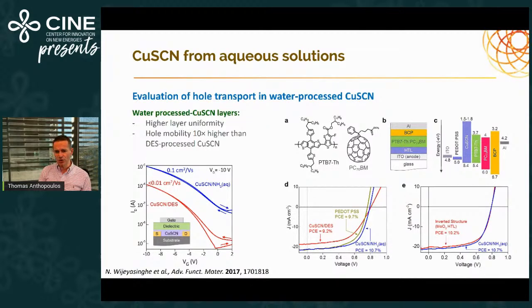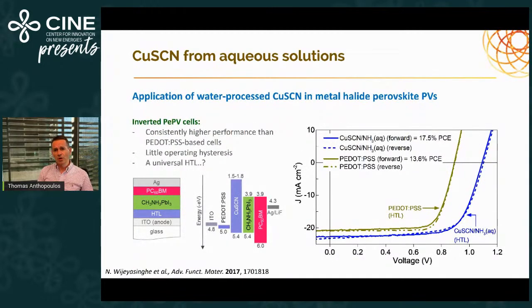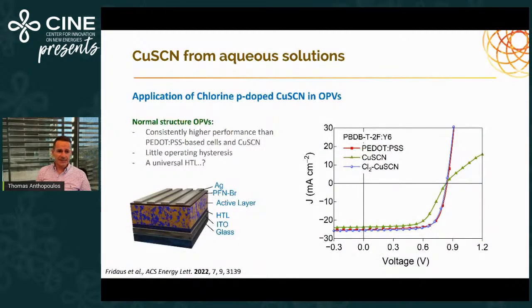And we're able to make also inverted cells, as well as extend this application to perovskite PVs. I think this data was at the time one of the highest efficiencies for a copper thiocyanate inverted cell, if I recall correctly. And this just demonstrated not only the potential of copper thiocyanate, but also the universality applicable to organics, but also to perovskites.